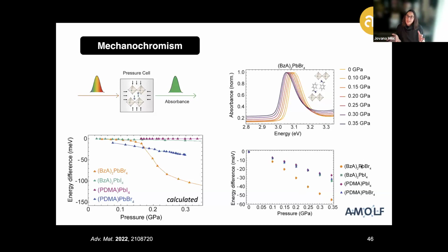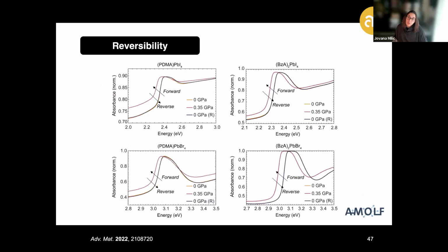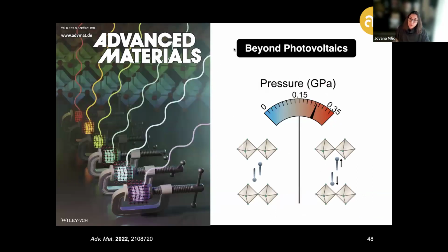Now most importantly, in the context of this study, these changes that are apparent for all different layered perovskite compositions are also found to be fully reversible within this pressure range, which means that the system reverts to its original configuration when reducing further the pressure, highlighting now the potential for the first time of these layered perovskite systems to feature such reversible mechanochromism.